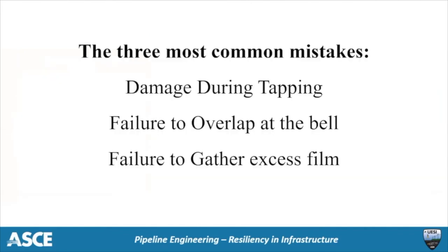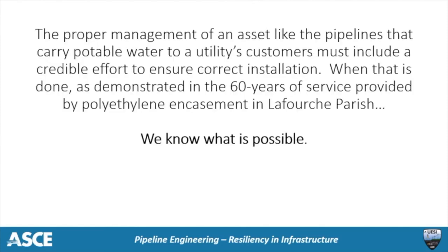We know with assurance that the film was installed properly in Lafourche Parish in 1958. Over the years, we've had the opportunity to investigate hundreds of similar installations and have found that the primary problems with the use of polyethylene encasement are related to damaging the film during tapping operations, failure of the contractor to overlap the film at the joint during installation, and failure to ensure a snug fit of the film to the pipe barrel along its entire length. But as shown in Lafourche Parish, these are not insurmountable problems.